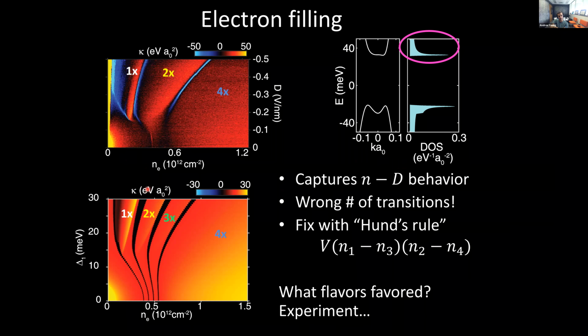If we do that, we can see that the basic behavior of these features more or less is mimicked by the Stoner model. They don't do much at low density, and then they go out to higher density as you increase the magnitude of this Van Hove singularity. So it captures the basic density versus displacement field behavior. Interestingly, it gives you the wrong number of transitions. It turns out you can fix this in a very natural way with a kind of Hund's coupling, just as in a shell filling of an atom, where you fill nominally degenerate states in a certain order because there's actually some difference in exchange between spins and valleys, or spins and orbitals in this case.